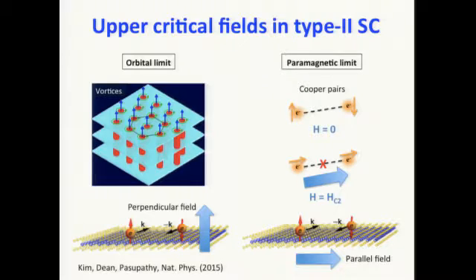And actually, what's special about this single layer material is that when you turn to an in-plane magnetic field, the orbital effect is completely quenched, because there's no more supercurrent circulation, since you only have one atom of material left. So the orbital limiting effect is completely quenched in the monolayer case for a parallel magnetic field. What comes after that is the spin paramagnetic limit. So it works in the following way.